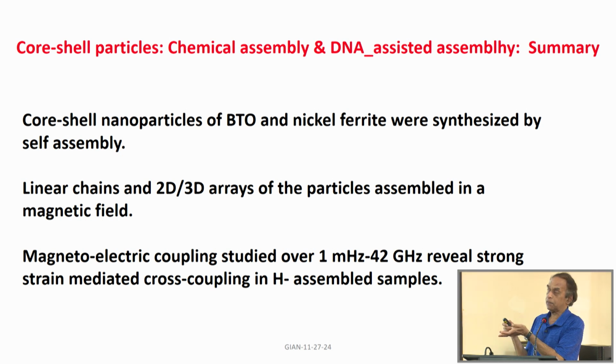2D as well as 3D, and we made measurements of the strength of the magnetoelectric interactions, and from the values that we got, we infer that there is indeed a strong magnetoelectric effect, but not with a strength anywhere close to bulk thick films or thin films of these composites. So that is the take-home message from this effort.